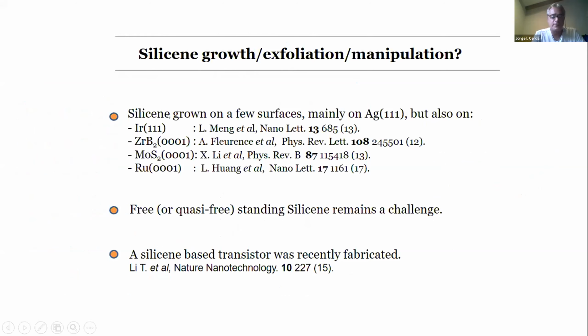Well, it's only been grown on a few surfaces, not like graphene. Apart from silver 111, which has been very well reproduced, it has been reported to be grown on these substrates. I'll talk about it if I have time at the very end of the talk. And as I say, there are a few hexagonal surfaces where it's been reported. However, free or even quasi-free standing silicene remains a challenge. I think it's too reactive, so it hasn't been achieved so far. There was a kind of breakthrough when they were able to build what they call a silicene-based transistor. It was a very complex process of transferring the silicene, and at the end they were able to make a transistor which didn't show very special properties, but it was still a breakthrough.